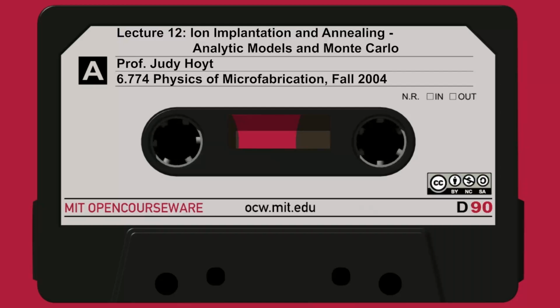And this is all 3 of these here in the upper left corner. These 3 are what we call analytic. They're based on these equations that we've been talking about. The Monte Carlo model is quite different, and we'll talk about that next time. With Monte Carlo, literally in the computer, you shoot ions into the crystal and you follow the scattering processes, and you see where all those ions end up. A computer can do that. It can sit there all day, and it can calculate the trajectories for 10,000 ions and then plot their statistical distribution. So Monte Carlo tends to be quite accurate if you have enough physics in. Unfortunately, it takes a long time because the computer has to go in there and follow every ion, see where it ended up.